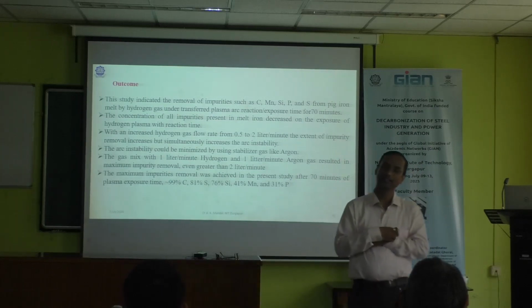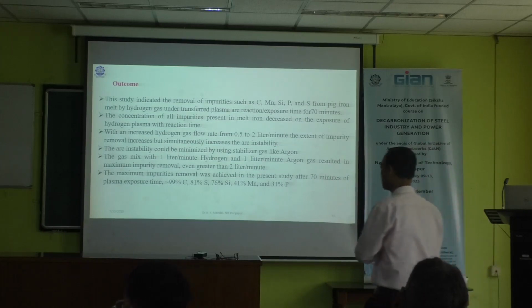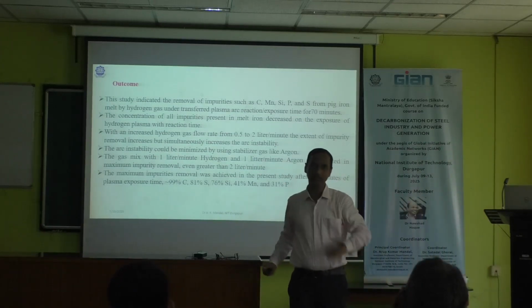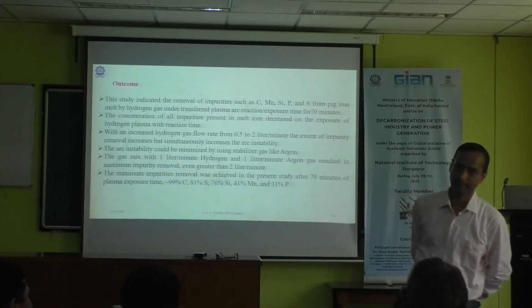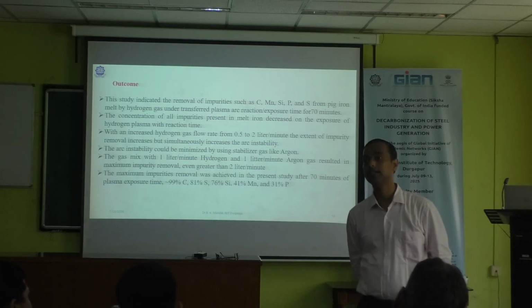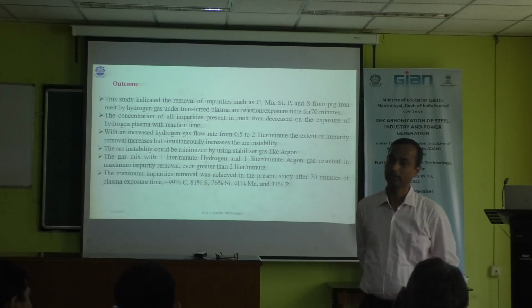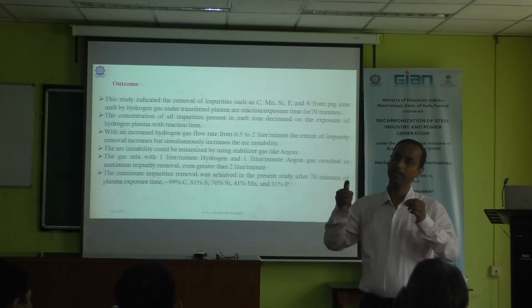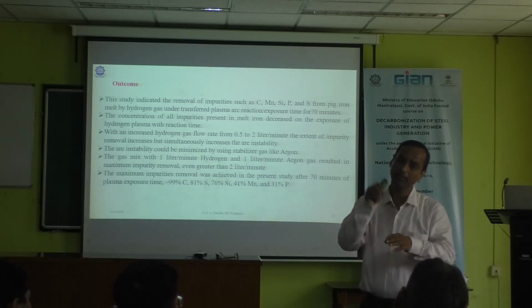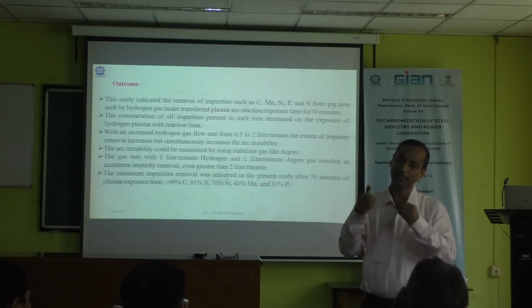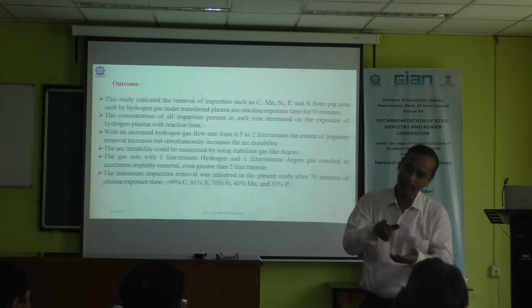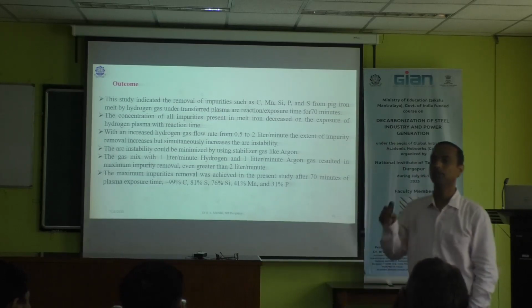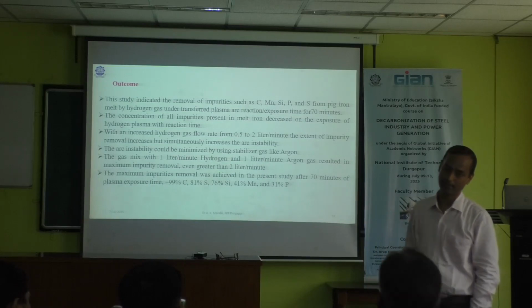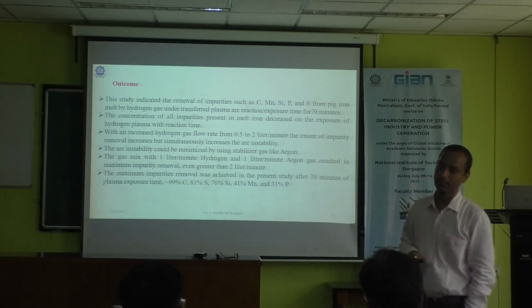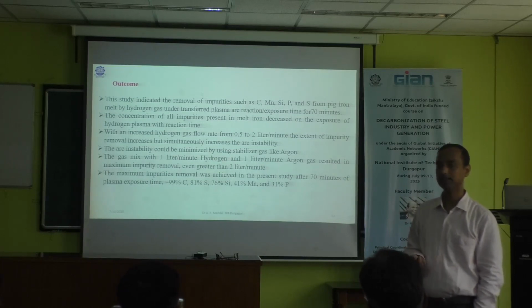Why should the arc get destabilized with increase in hydrogen? Hydrogen is not a stabilizing gas. In arc welding also you can see shielding gas and stabilizer gas, both gases are there. So argon will make the arc stable, a continuous arc. Otherwise, sometimes it will be continuous, sometimes it will be disconnected, and again you have to adjust the electrodes. If you only give hydrogen, then it will not be a stabilized process. But if you provide some amount of stabilizer gas, the arc will be stable. If the arc is stable, then heat generation will be high.